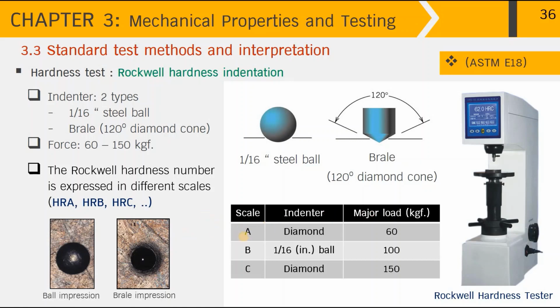For example, on scale A, we have to use the diamond or the Brale indenter and also apply the major load of 60 kg force. And for scale B, we now change into a steel ball indenter while increasing the major load up to 100 kg force. For scale C, which is suitable for surface hardened steels, we use the diamond or the Brale indenter with the major load of 150 kg force.